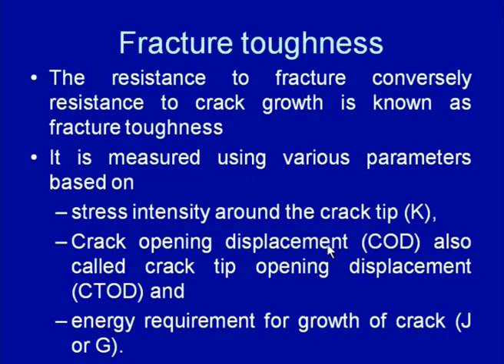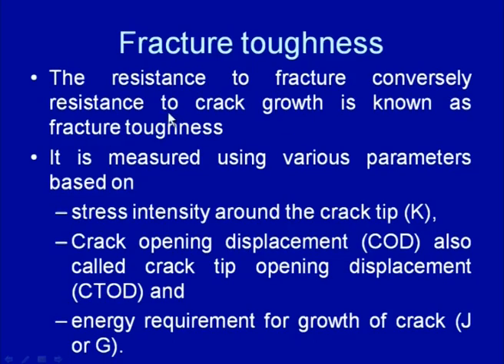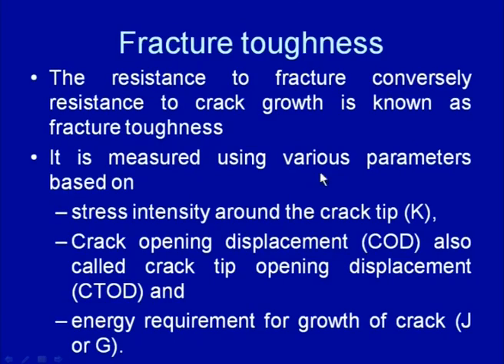Then the fracture toughness test is another important test which is commonly used for measuring the resistance to fracture of the material. Indirectly it shows that if a crack is present, then under what conditions it will start growing. So, the resistance to crack growth is measured in terms of the fracture toughness. It is measured using various approaches, like the stress intensity factor around the crack tip, commonly denoted by K.